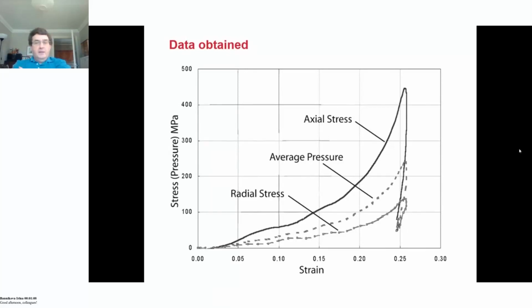You can see that the axial stress, or the stress along the rod, gets up to be quite high, kind of 500 megapascals. The radial stress we measure follows a very similar behavior, but it's radial stress, so it doesn't go as high in terms of the levels there, only to about 130 megapascals. If you said, well, what is the average pressure in the system? You would do a weighted average along the axial stress and the radial stress and come up with the average pressure. This is a response.